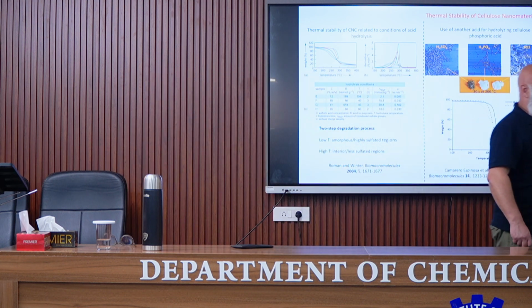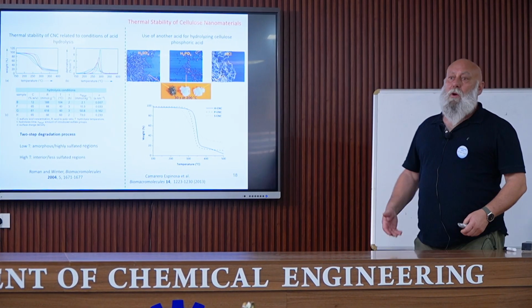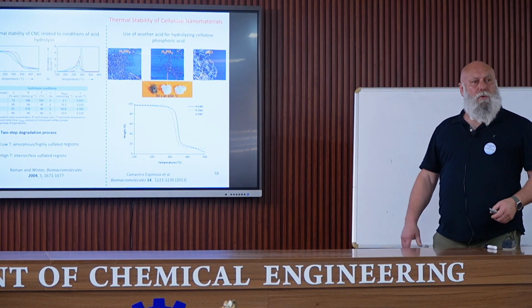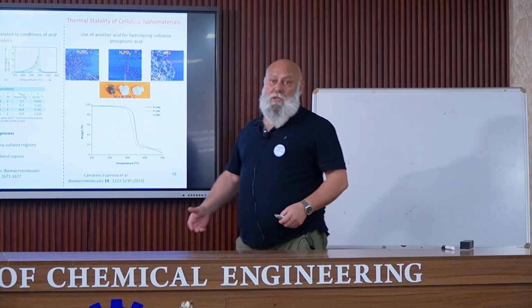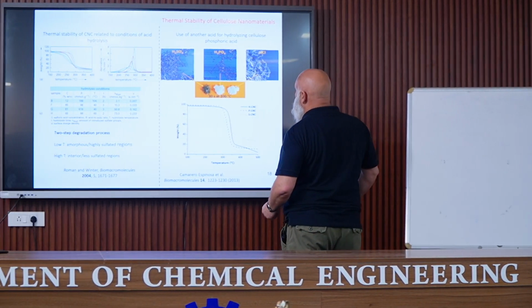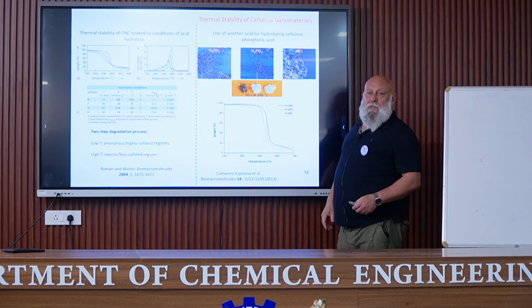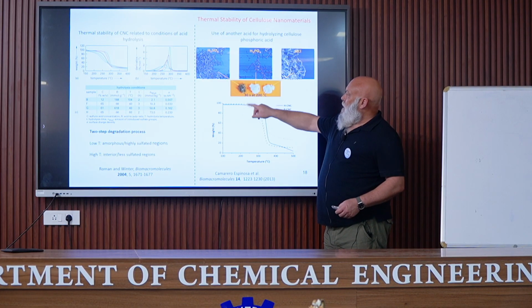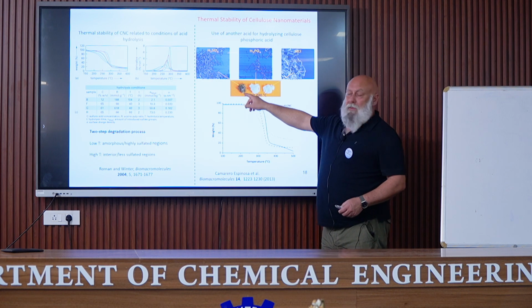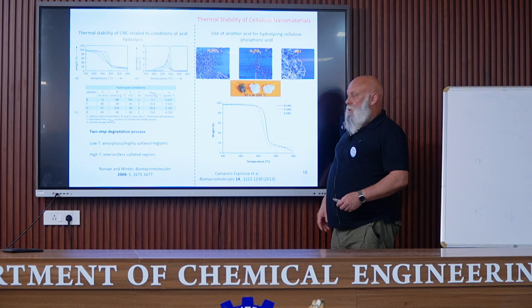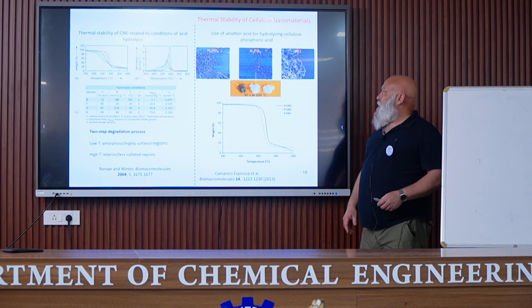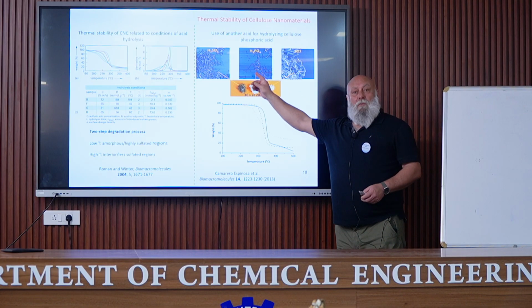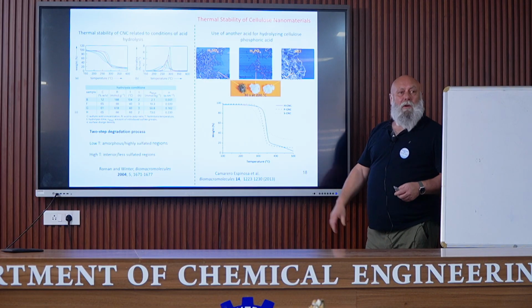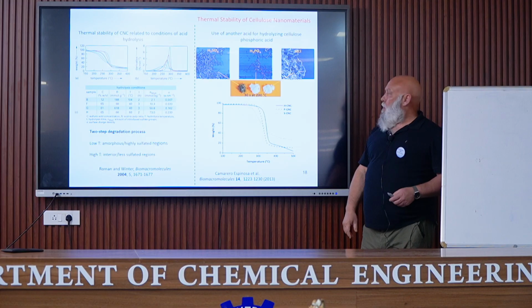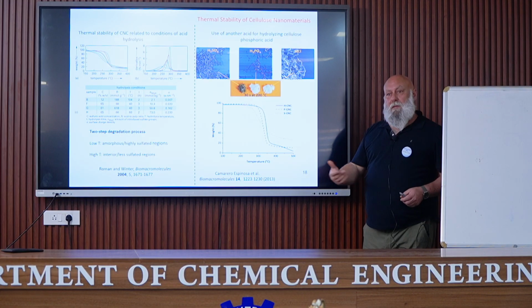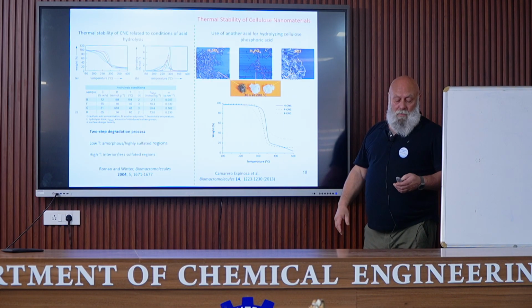So, what are the possibilities to avoid this early thermal degradation? Hydrochloric acid can be used, but the problem is that the suspension is not stable. But it avoids the degradation. You can see cellulose nanocrystals that were obtained from sulfuric acid that were heated during 30 seconds at 200 degrees, it's brown. With hydrochloric acid, it's white. It's not degraded. And we can see this also from a TGA experiment. Phosphoric acid was proposed because we have a better stability of the suspension compared to hydrochloric acid, and the degradation is similar to that with hydrochloric acid.